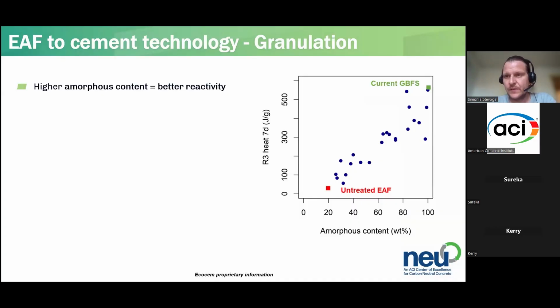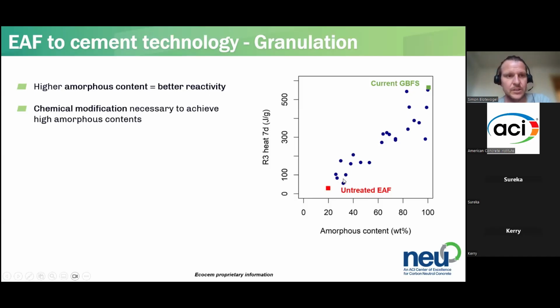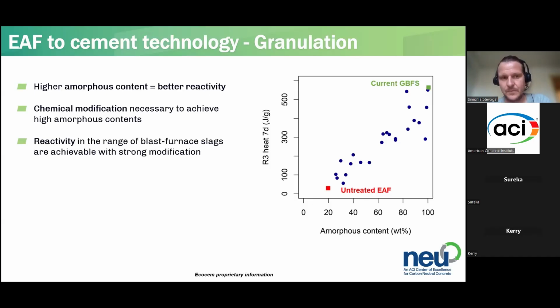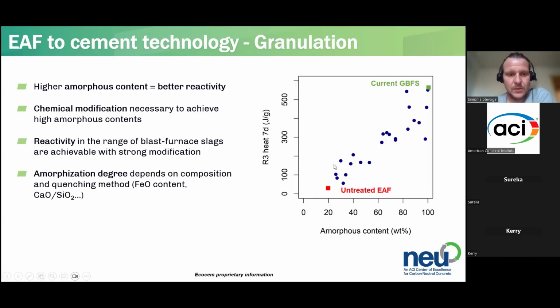I already said that higher amorphous content is likely very, very interesting for reactivity, and we would base that on R3 tests for the moment. We've done quite a lot of mixes in the laboratory, and we get out basically, if you get it all amorphous, you get closer to a blast furnace slag, and you start something very low here. And the amorphization very much depends on chemical modifications. This mainly concerns network former addition, but also reduction of iron in some cases. So if you dilute enough to have low iron contents, you get better amorphization. If you adapt the calcium-silicon ratio in a range that is easily vitrifiable, you will get higher amorphous content, and that yields directly higher R3 reactivity.